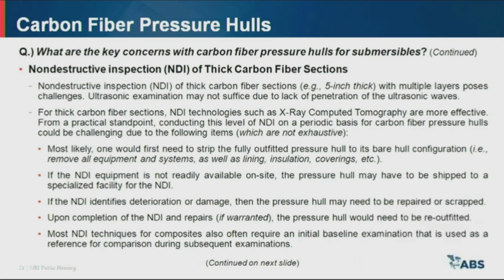So for thick carbon fiber composite sections, you will use non-destructive techniques such as X-ray computed tomography, or you can use active thermography, okay? So X-ray computed tomography, basically you have an X-ray machine that goes around the circumference of the pressure hull, and you have various slices. You have images in slices. All these images are combined together using software, and you get a 3D image of the hull, okay? Then you have an in-depth look at what is going on inside the hull.